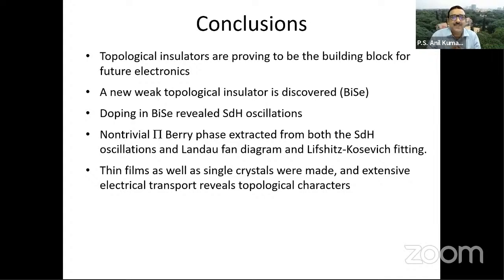We also found that if you start doping, for example, we got 8% doping of antimony into this bismuth selenide, we started getting these Shubnikov oscillations, and that gave us a lot of important information that you have a pi Berry phase in the system, and we could also enhance the mobility of the system to around 15,000. We keep trying to increase the mobility. So now we are also working towards doing further doping at different sites to make sure that the carrier concentration comes even further down, so that you get the proper bulk insulating material as well. And we are exploring both thin films as well as single crystals for this study.